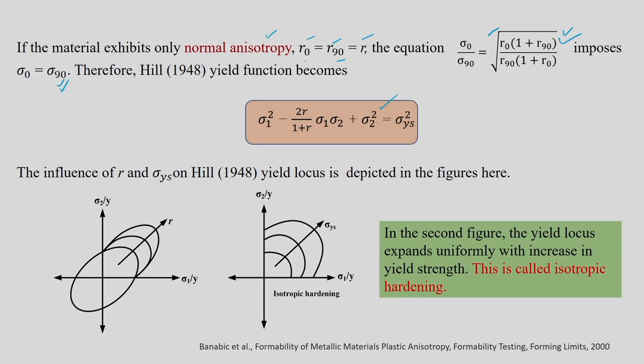So, now this equation can be used to check the effect of R and sigma ys on the locus. And what is the effect of R? You see that the x and y axes are actually normalized values, sigma 1 by y and sigma 2 by y, and you will see that by increasing the R value diagonally, the yield locus is going to elongate. That is one, which we have seen before also. In the next one, if you increase the yield strength, it simply means that the yield locus is going to expand uniformly in the outward direction,